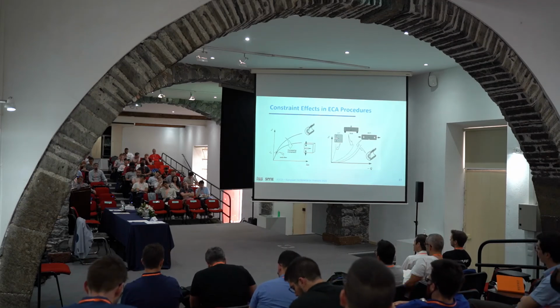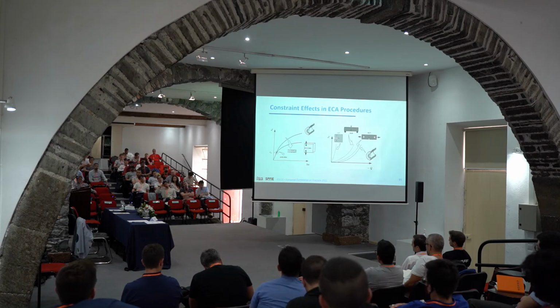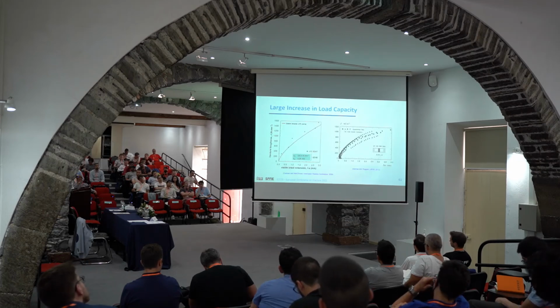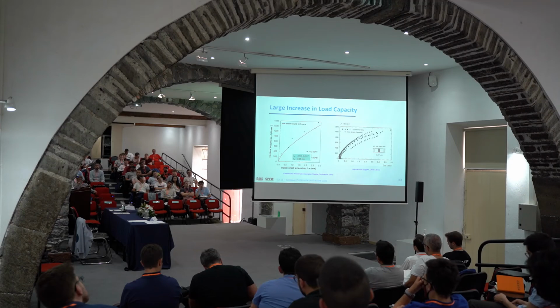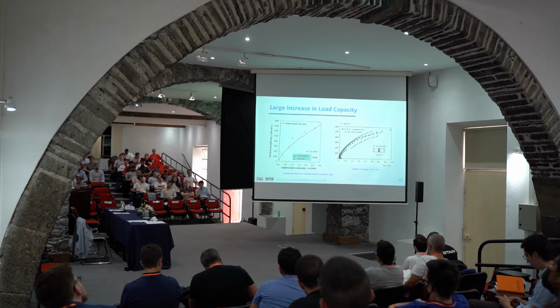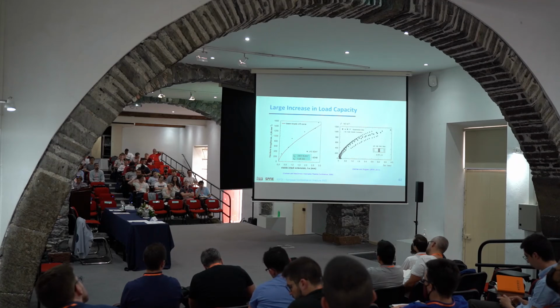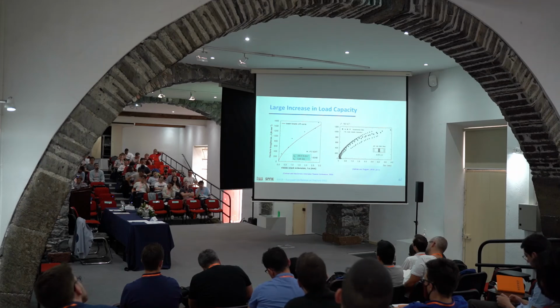Okay? So that's why a very bad idea is to use the CT, because you see here the curves of the SE(T) are much closer to the curve of the pipe. Okay? So the SE(T) is the standard nowadays for evaluating fracture toughness properties for pipelines. And actually, it's so good that other areas are starting to use this, because it's less severe than the CT.